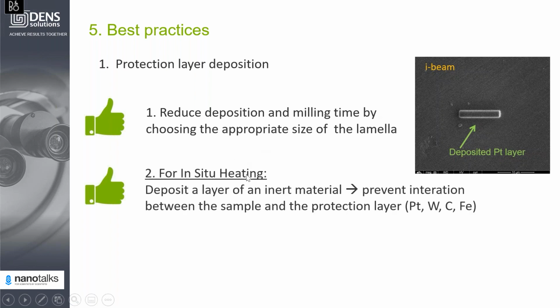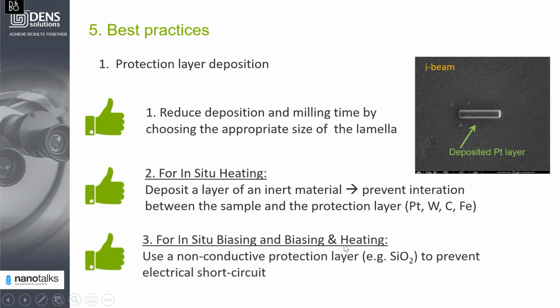Specifically for heating experiments, if you suspect that your protection layer will interact with your sample, it's better to put an additional material in between the sample and the protection layer. For biasing experiments, to avoid short circuits, instead of platinum, tungsten, or iron, it's probably better to use a non-conductive protection layer like silicon oxide.